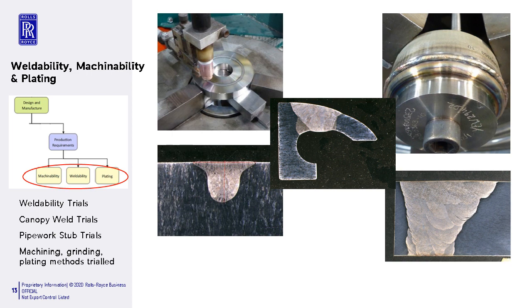Finally, in terms of leg one, we also carried out a number of trials reviewing standard production methods, including weldability, reviewing weld width to depth ratios, and also trials both on automated and manual welding of canopy and fillet welds. All trial welds were assessed via mechanical properties, microstructure, and corrosion resistance, all with the expectation to confirm that the existing weld procedures remain suitable and can be applied without change. Also, as part of this leg, we confirmed that the material performs as expected when applying traditional machining, grinding, and plating methods, and the results were equal to its wrought equivalent.